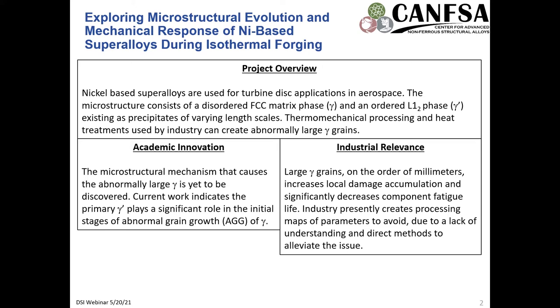And from an industrial perspective, the relevance of this project is that these large gamma grains, on the order of millimeters in diameter, can increase local damage accumulation at high temperature operation conditions, and significantly decrease the reliability and the life of the component. And we're really trying to understand the mechanisms, but what's currently done in industry is they create processing maps of parameters to try to avoid, although through complex shapes of the components, usually there are some regions that are unavoidable.